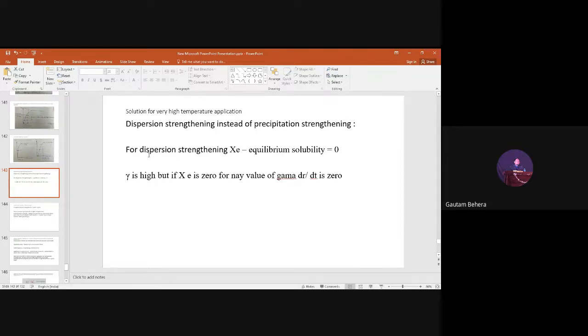Yeah, already I have written. What is the reason behind the strengthening? You can see for dispersion strengthening, Xe, the equilibrium solubility, is 0. So these oxide particles, TiO2, yttrium oxides, thorium oxides, will not become soluble in the matrix. So if they do not become soluble in the matrix, what will happen? Strength will remain more. They will not become coarser, right?